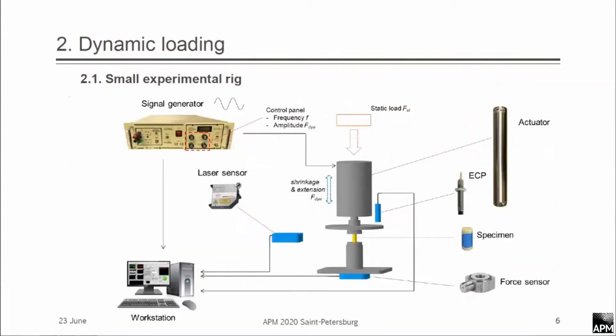In order to see how different the mechanical properties will be in dynamic loading, we designed a small experimental rig, which is presented on this slide. Here in the middle, you might see the sample loaded by a constant static weight, and by dynamic force produced using a magnetostrictive actuator powered by a generated signal, at which we could change frequency and amplitude. During the experiment, it was shrinking and extending, applying dynamic load just on top of the sample. Two sensors recorded the sample's deformation: a laser sensor and an eddy current probe. The laser was for horizontal displacement, and the eddy current probe for vertical strain.